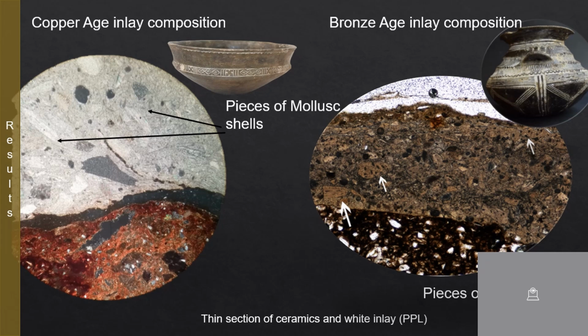Thin-section microscopy further supported these findings, revealing distinct differences in composition and texture between Copper and Bronze Age inlays. Copper Age inlays were composed of fine-grained carbonate paste with characteristic mollusk shell fragments, while Bronze Age inlays contained poorly sorted bone fragments with fibrous microstructures and occasional mineral inclusions.